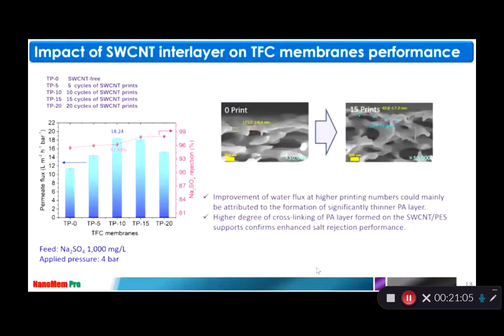So yeah, this is our overall performance. We found that with different cycles, the permeate flux and sodium sulfate rejection change. You can see the different SEM images from 10 to 15 times. So we achieved around 97.88% rejection, and the highest flux of 18.24 LMH per bar.